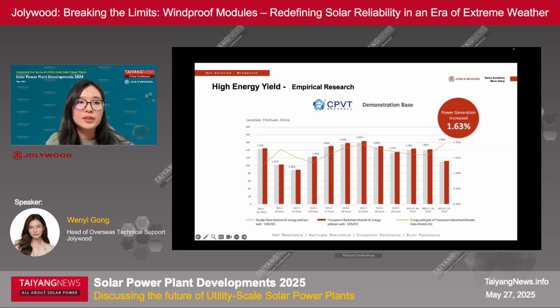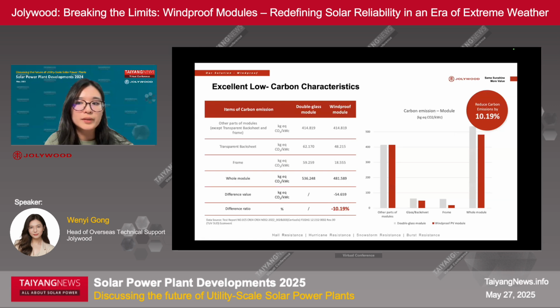And in the end, the carbon emission performance is also much better than the double glass. Due to less use of glass, and also because steel production uses much less electricity than aluminum, the carbon emission of the backbone steel frame is much lower than the aluminum frame. So combining all of the components, the carbon emission for the windproof module is more than 10% lower than the conventional module.